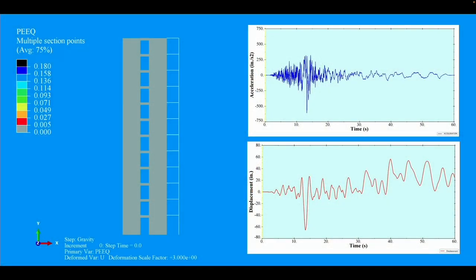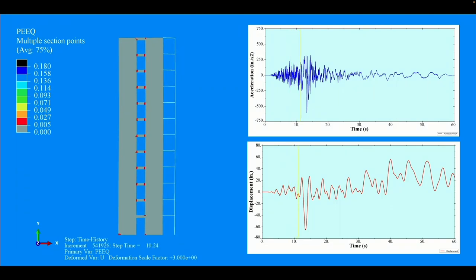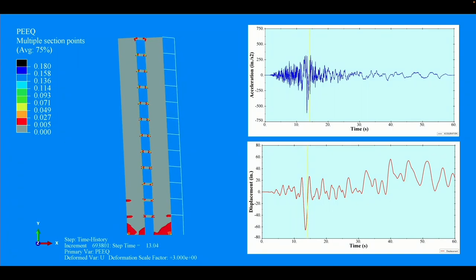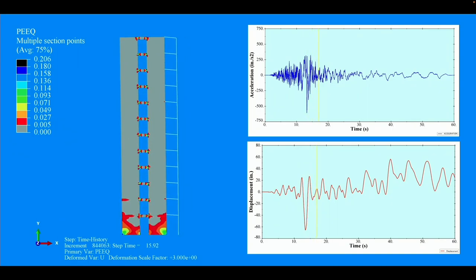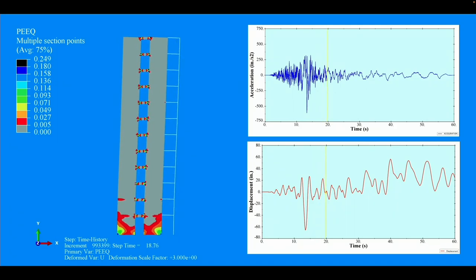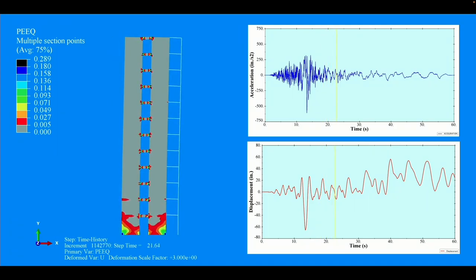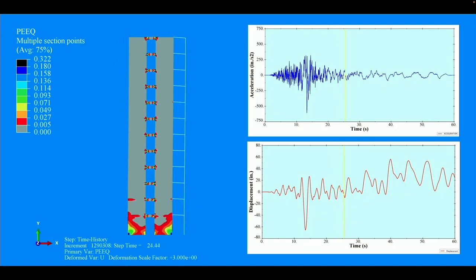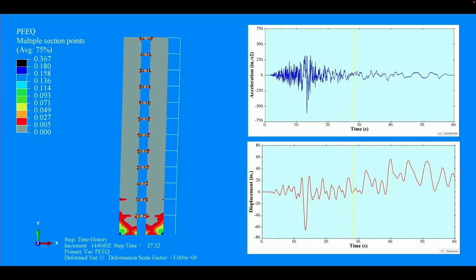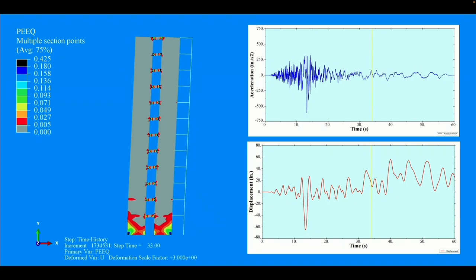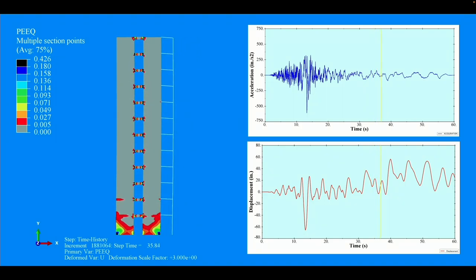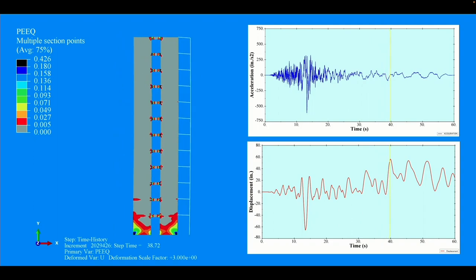This is a video that actually shows the seismic response of a 12-story structure where you can see the ground motion as it's tracking through, and you're seeing the response of the system. And all of these red spots are the occurrence of yielding along the height of the structure. There's the big pulse that causes all kinds of yielding along the height of the structure. And when the shading turns black, that's when you're getting close to fracture in the coupling beams, which has occurred for some of these coupling beams along the height. Remember, this is the failure level earthquake, but the system remains stable and survives the entire failure level earthquake with some occurrence of fracture initiation at the base of the walls at the end.